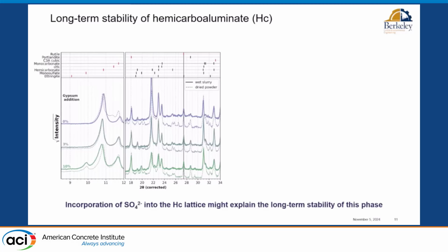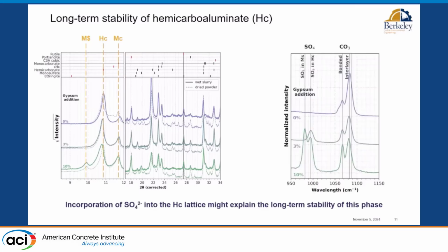If you have only 3% sulfate, we still see only carboaluminates. We do not see the line for monosulfate, which is here. And we used Raman actually to observe and confirm that there is sulfate being incorporated in the lattice of hemicarboaluminates, and we believe that this is the reason why in real LC3 systems, hemicarboaluminate exhibits long-term stability, which is something that we do not see in the database that we have right now. So basically that's a reason to update the database. We probably need more data to do that. But that's the mechanism and the explanation that we have so far.